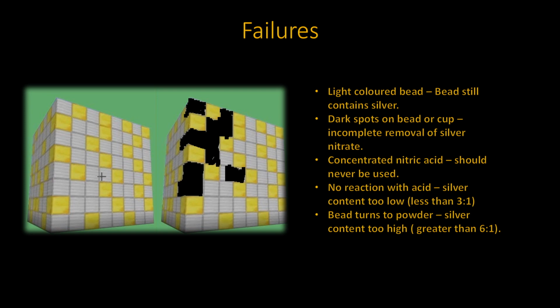The graphic depicts the removal of the silver from a bead. The silver atoms and the gold atoms are randomly displaced throughout the bead. As the silver is dissolved, it leaves microscopic holes throughout the remaining bead. The bead will not have a solid, defined structure. It is said to be amorphous. This is the reason why the bead may break down into a powder or just simply break up. This is the reason why the bead is annealed. That process will be discussed later in this presentation.